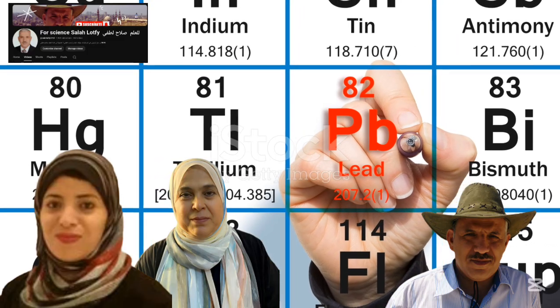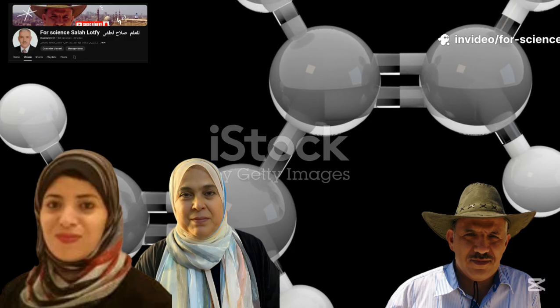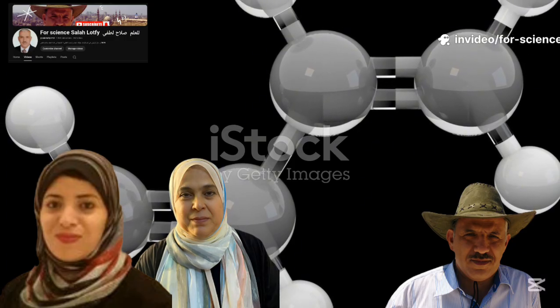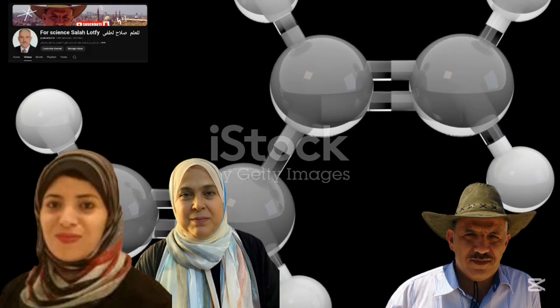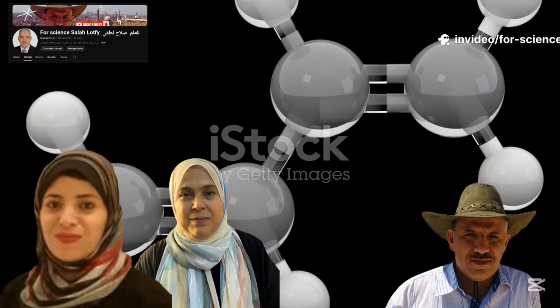Each doped ion contributed in a unique way to the structure and shielding performance. Cerium, Ce3+/Ce4+. With its ability to switch valence states, cerium created more connected bonds, stabilized defect centers, and relaxed the glass structure after irradiation. This explains why Ce-doped lead borate glass showed the highest radiation shielding efficiency.